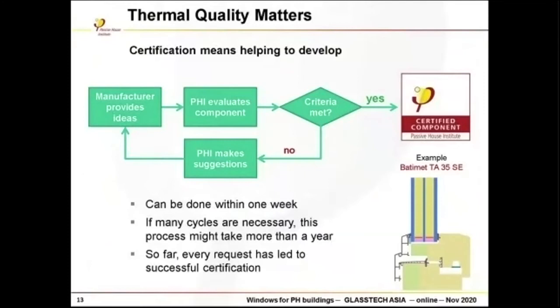Well, what we do with certification, in principle, it's quite simple. We check your product, your window, and then look if the criteria are met, and we do it by looking for the thermal flux through this part. And if our criteria are met, we can give a certificate. If not, we make suggestions how to get the window better, with better insulation and lower thermal bridges and so on. And then you can go for the next turn for the certificate.